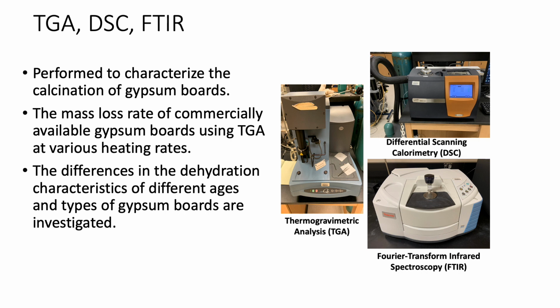In addition, thermogravimetric analysis, differential scanning calorimetry, and Fourier transform infrared spectroscopy were also conducted. The TGA results gave the mass loss as a function of temperature for different heating rates. This helps us develop variable heating rate thermochemistry models. DSC will give us effective heat capacity, and FTIR is useful to understand the effect of calcination by doing FTIR analysis of gypsum samples exposed to heat flux and not exposed to heat flux.